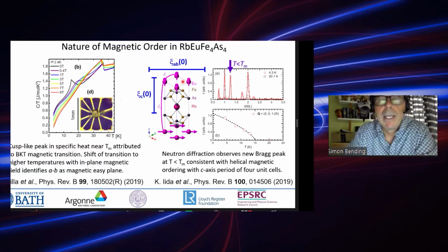So you would expect actually quite a strong interaction, and certainly these are not in the limit where you would expect any averaging of the moments or the exchange interaction over one or more unit cells, which are one or more periods of this helical magnetic order, which is actually 4 unit cells high. That's very much larger than the superconducting coherence length that we're dealing with here. So it's an interesting situation. It doesn't really correspond to either example that I started with. It's not a ferromagnetic superconductor, but equally well, it's not an ensemble averaging antiferromagnetic superconductor either.